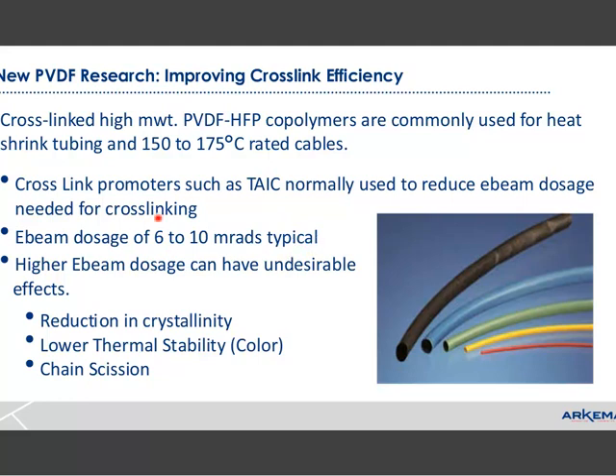And there's always a desire to reduce the amount of radiation dosage because it does affect color, and higher dosage can cause reduction in crystallinity, lower thermal stabilities, and chain scission. So there is a benefit to the industry of having products that perform better.